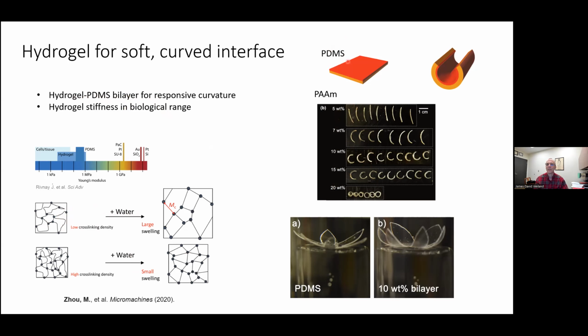If you have a layer of PDMS on the top and the hydrogel on the bottom, and they're chemically linked, so that boundary is chemically bonded, and if the hydrogel swells, then that will force a curved shape, because this bond restricts the ability of the hydrogel to swell in one direction. So it exerts a force that causes this type of shape.